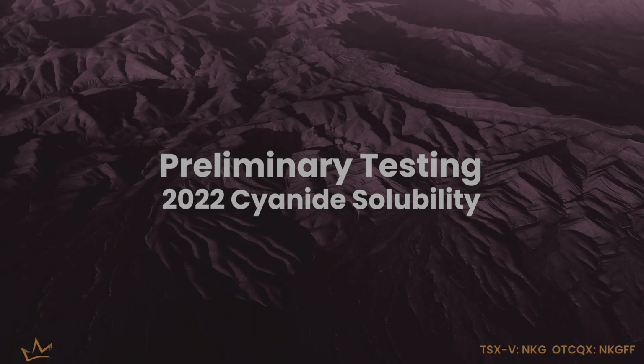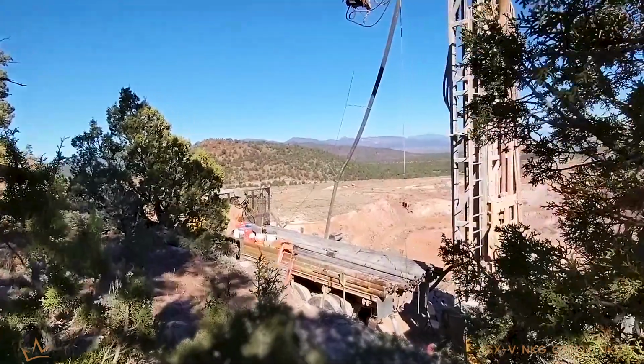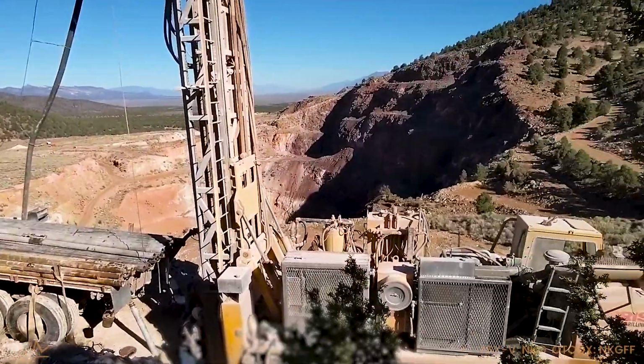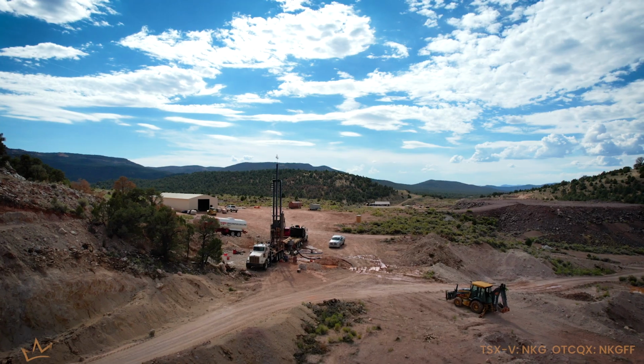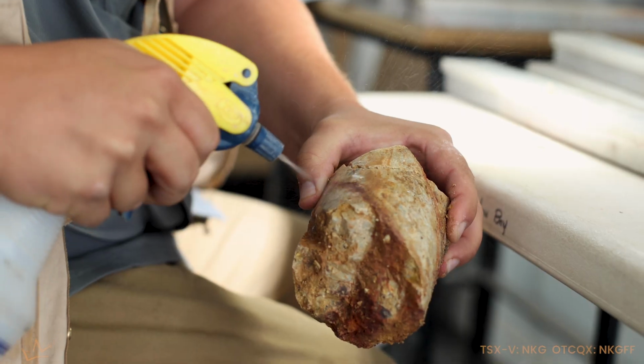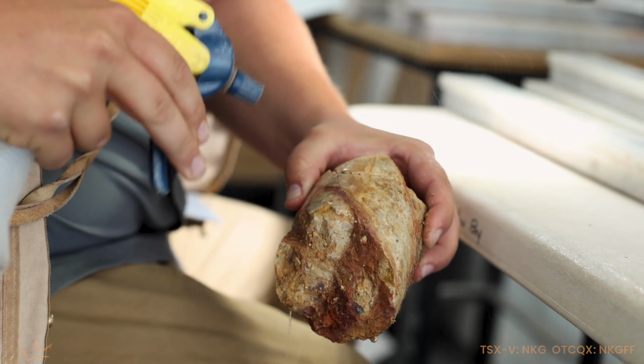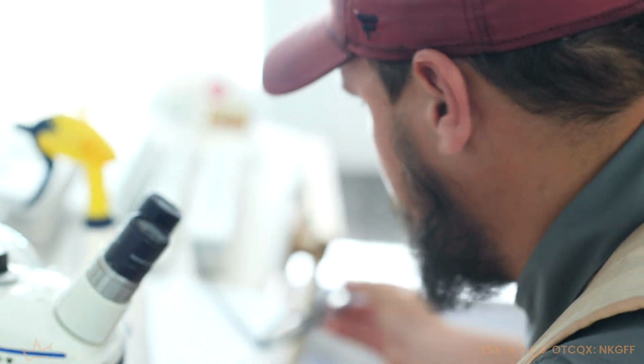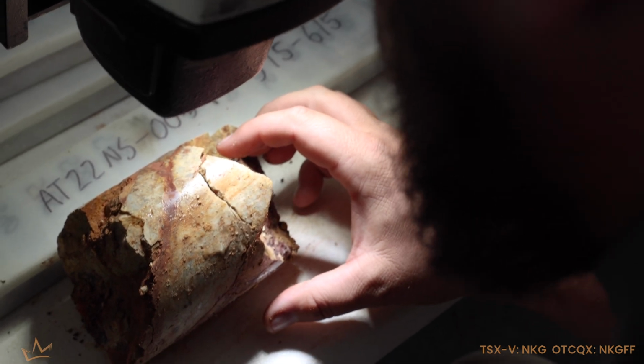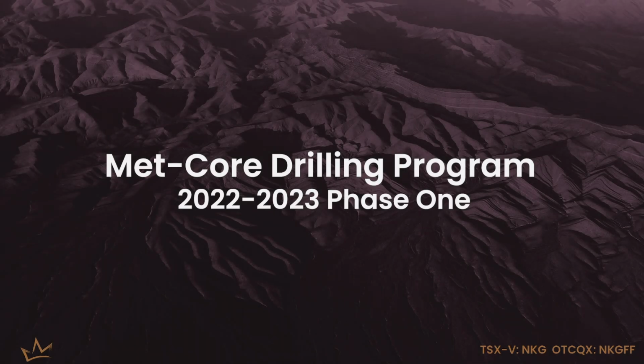To start, we pulled a few thousand assay samples and had them run to the lab for cyanide solubility to find out whether this deposit that they were drilling was an oxide deposit or a sulfide deposit or a mixed deposit. And essentially what those results told us is everything that they were drilling, with the exception of a pretty small portion, was all oxide and didn't show any evidence of carbon of any significance or anything like that. So knowing it was oxide and fairly simple, we decided to go ahead with the bulk sampling and a phase 1 met core drilling program.